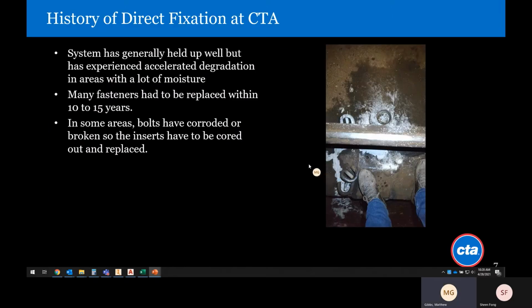So the system generally held up fairly well, but in areas where we have a lot of moisture, we have experienced accelerated degradation of the fastening system. And so within the last few years, after about 10 to 15 years of service, some were even sooner, we had to replace quite a few fasteners in order to maintain the track system. And these areas often experience heavy rail-based corrosion, and then the fasteners deteriorate.